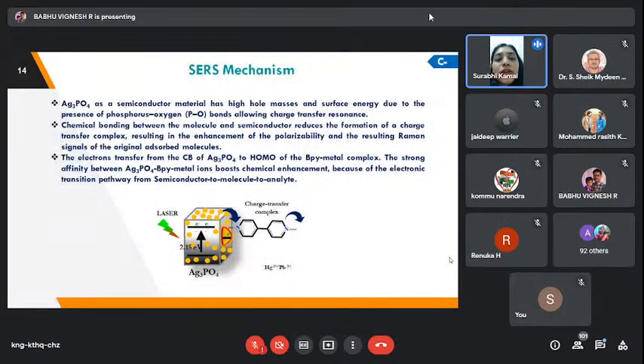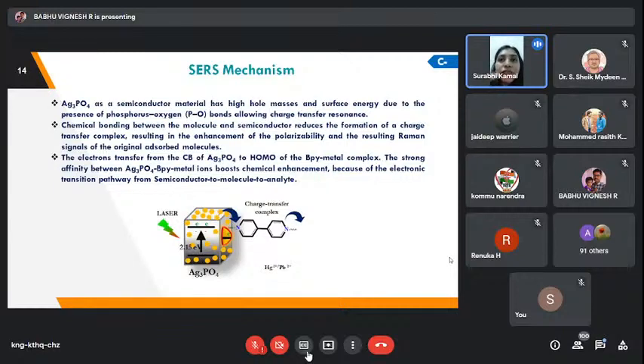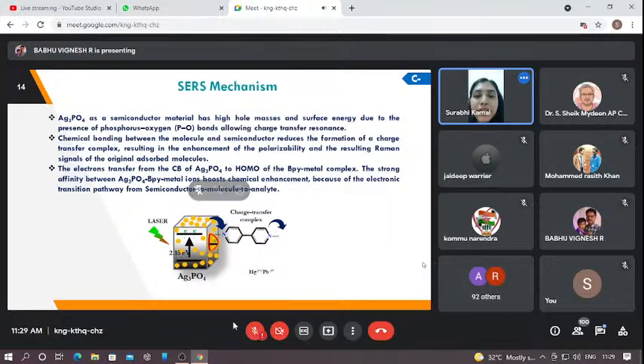Next I talk about the proposed mechanism of this SERS enhancement. Silver phosphate, as a semiconductor material, has a high hole mass and surface energy due to the presence of the phosphate P-O bond, allowing the charge transfer process. The chemical bonding between the molecule and the semiconductor promotes the formation of the charge transfer complex, resulting in enhancement of the Raman intensity, along with electron transfer inside the silver phosphate itself. So there is a double charge transfer, which is very helpful for the SERS enhancement.